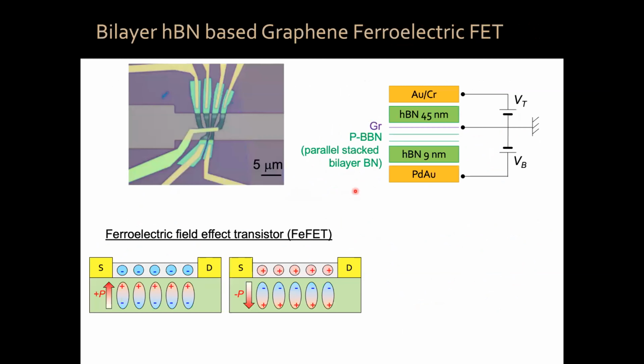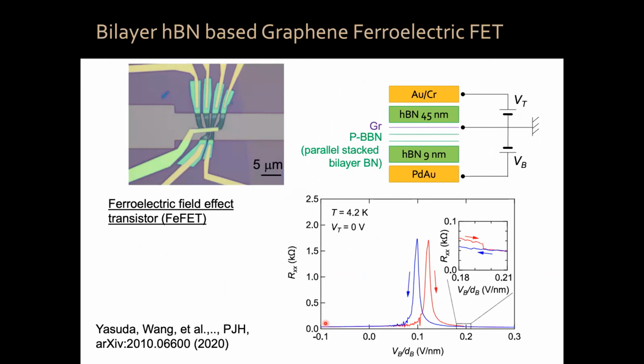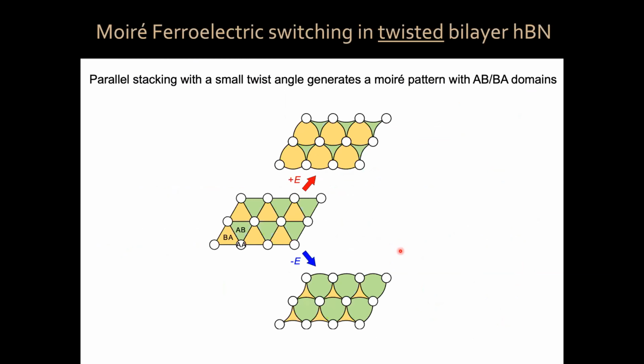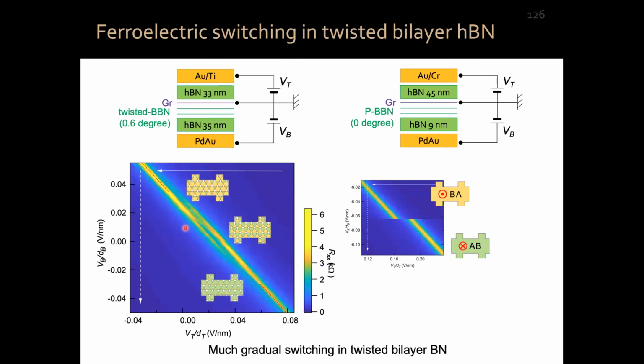We can make ferroelectric field effect transistors based on this. I'm going to go fast because I'm running out of time, but just show you that by putting a graphene sheet on top of this parallel-stack hBN, you sweep in one direction or the other, and you make a ferroelectric field effect transistor. This is the world's thinnest ferroelectric, less than 1 nanometer in thickness. You can also make a small angle rather than parallel stacking, and you make a moiré ferroelectric that you can switch with an electric field. These are the data showing that switching. Let me skip it. I will be happy to answer questions if you want.